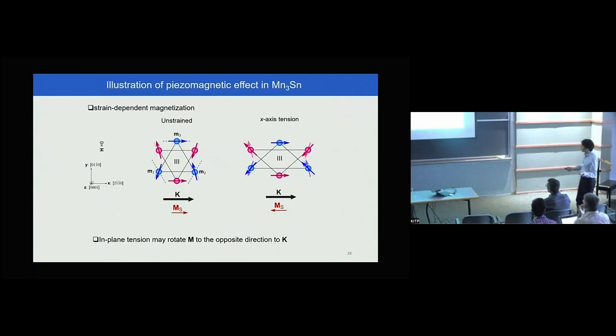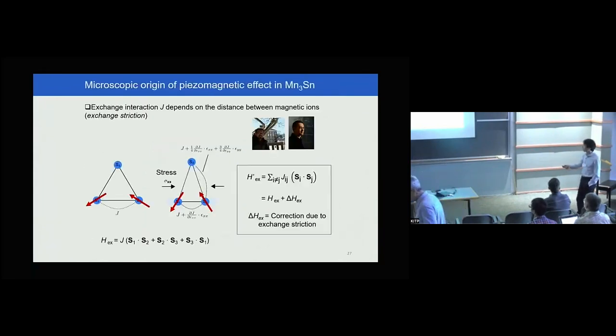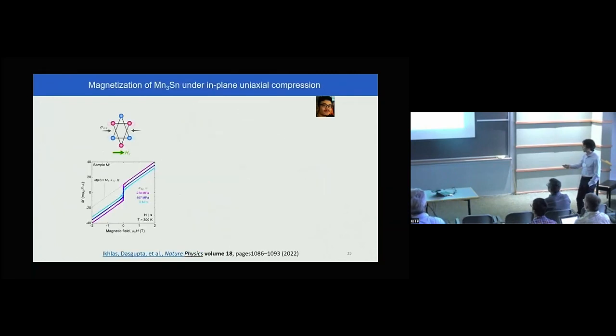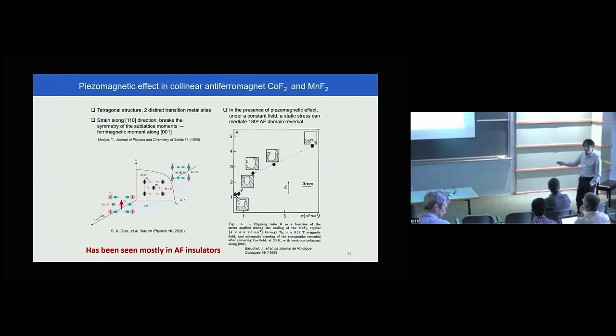And your question is whether this can be applied to other systems. So yes, if there is any symmetry that is broken, or if there are several different magnetic sites, you might be able to induce a ferri state, maybe for a different reason. In this case, ligands have a strong impact on the magnetization direction, which is different from one site to the other. It was fully compensated, but a small amount of strain can give rise to the ferromagnetic state. It sounds very general, because a 180-degree structure is the one you're describing. Yes. And if you use a magnetic field, you can stabilize one of those and apply strain, then you should be able to mediate this 180-degree spin reversal.